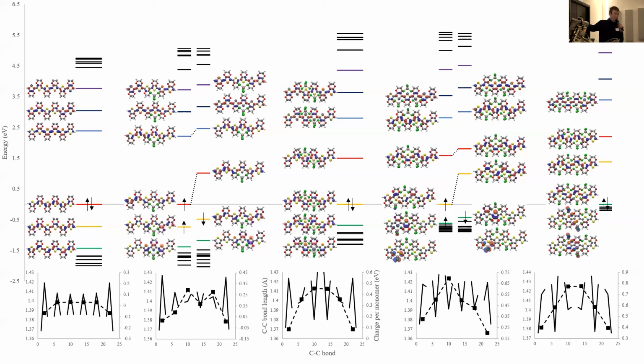For the undoped system, you can see that the middle bond of each monomer unit is long. That's the single bond. It's only got 1 electron in that bond, and as a result, the bond is slightly longer. You have the double bonds either side. The extra electron makes a stronger bond, drawing those atoms closer together. When you bring in an anion, it inverts the bond structure there. This is all completely conventional so far. They knew this right at the start.